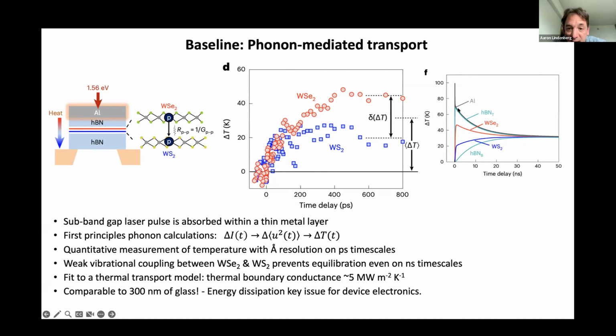And in fact, you can compare this to simulations, essentially solving the heat diffusion equation across these layers. I shouldn't call them first principles. And you can show that this equilibration process is really not occurring until timescales of order many tens of nanoseconds, longer than we can actually probe in these experiments.